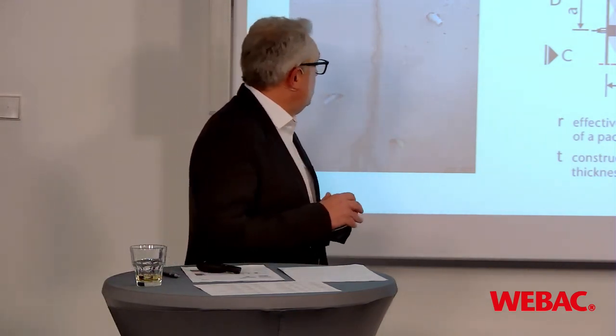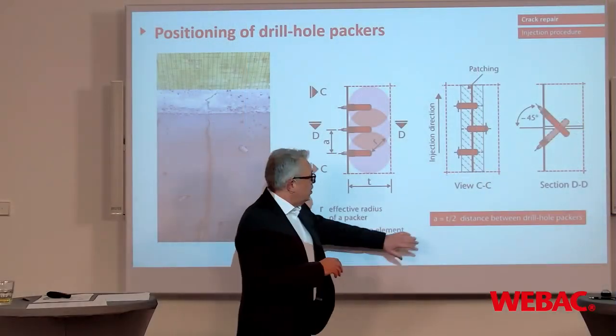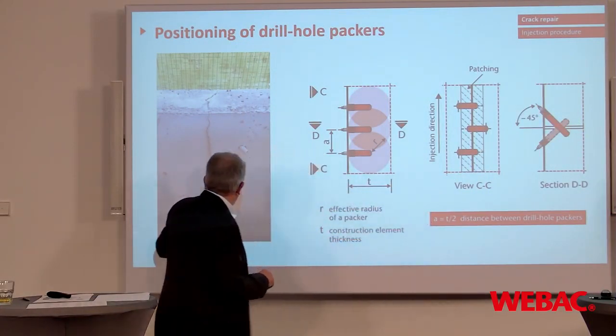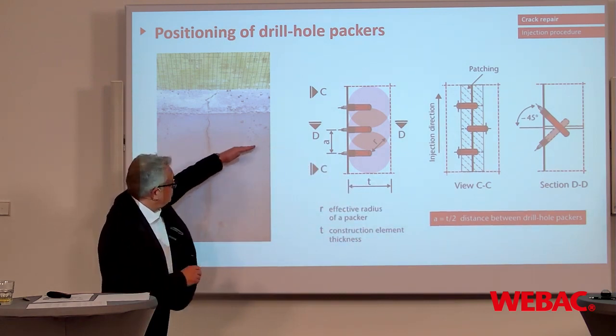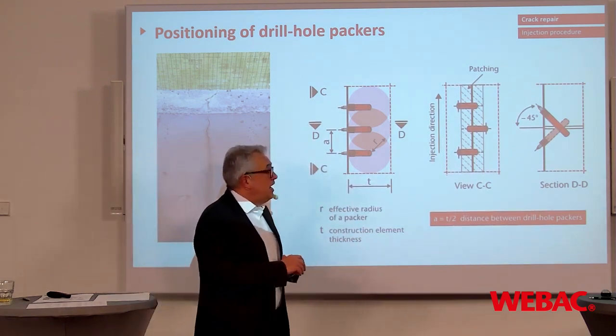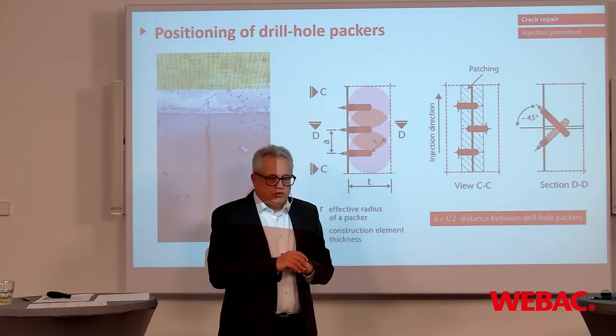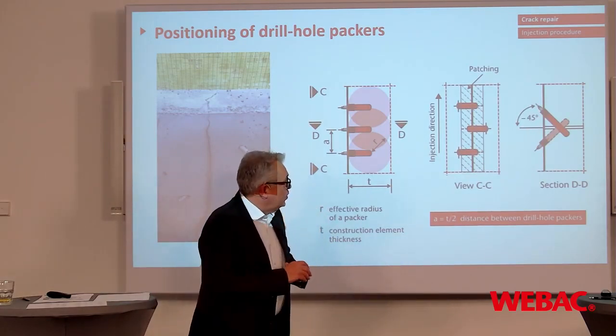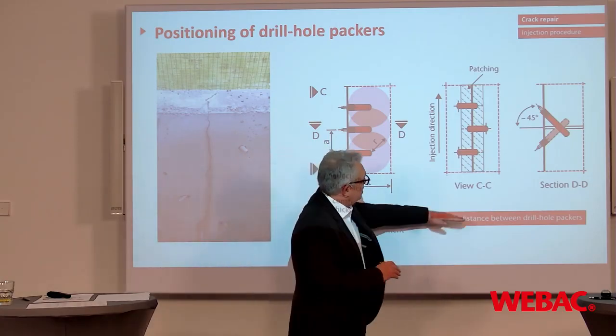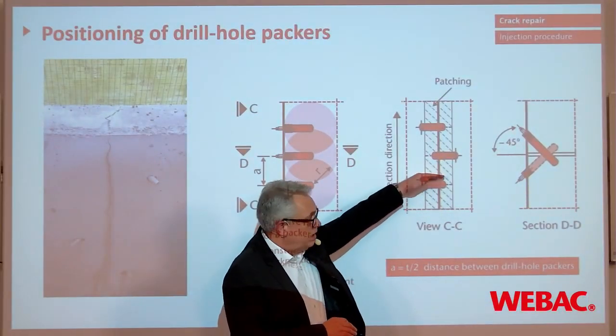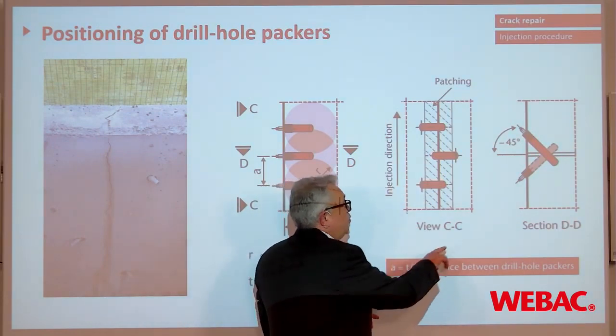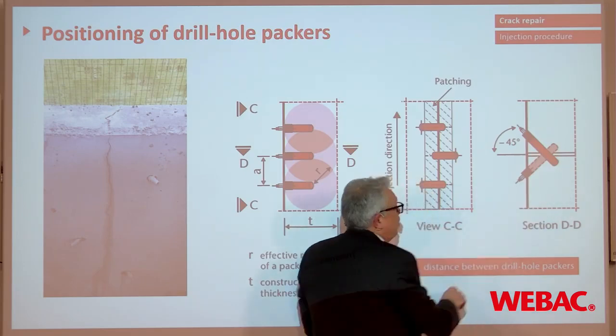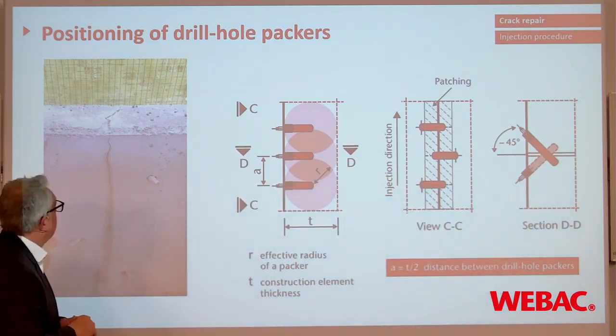In comparison to the impregnation, we find the pressurized injection with drill hole packers. So you find in the standard and norms, or we often get the question, what should be the distance between the packers? So the distance between the packers should be roughly half of the construction thickness. We should always inject from the lower part to the upper part. That's very important. And we should drill into the concrete at an angle of 45 degrees.